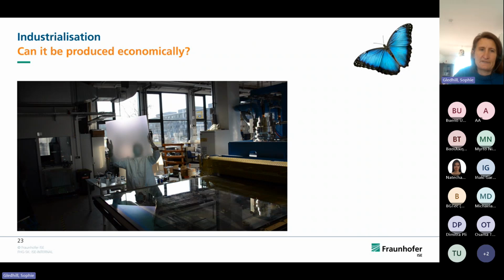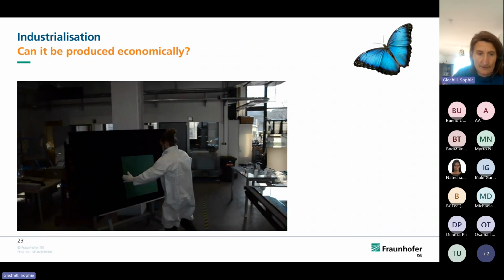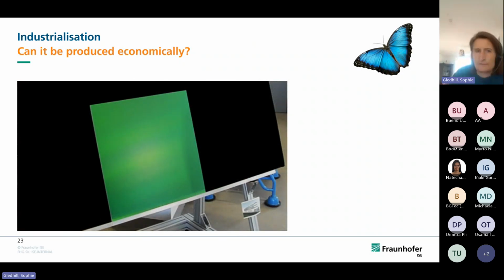Of course, everything's been speeded up. He lifts it up, and you can see it's transparent in transmittance. But when you put it on a dark absorbing background, we have this lovely green color with our selectively reflective reflectance. So the conclusion: yes, sputtering is already used, every glass window in Northern Europe has a low emissivity coating on. And although the morphocolor coating is thicker, it's definitely an upscalable manufacturable process.